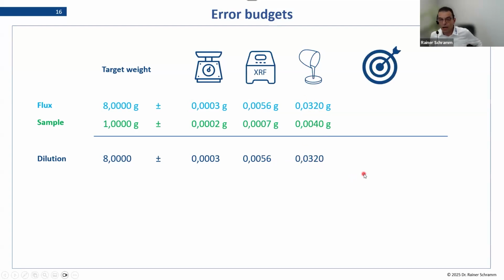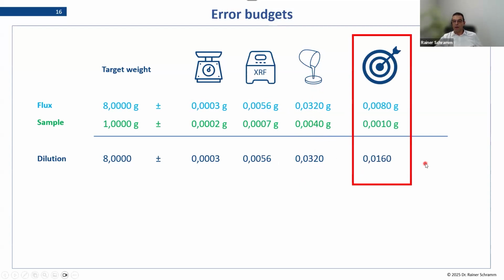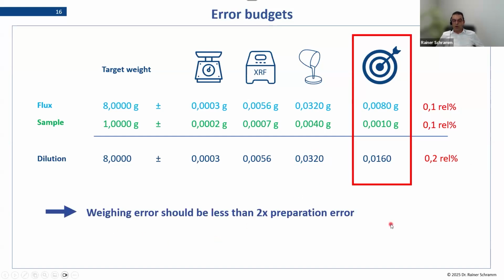And so the question now is, if I train my lab people, how precisely do they have to weigh so that this final error is not affected, because this is the error we get anyway, which is not part of the weighing. Our recommendation is that you should be in a range of 0.1% relative for flux and sample, so that if both add and vary, you have 0.2% error on the dilution factor. So you are still at half of the preparation error you will see anyway. So the rule is: keep your weighing error 2 times lower than your preparation error, then you are still good enough. But it has no influence on your final result.